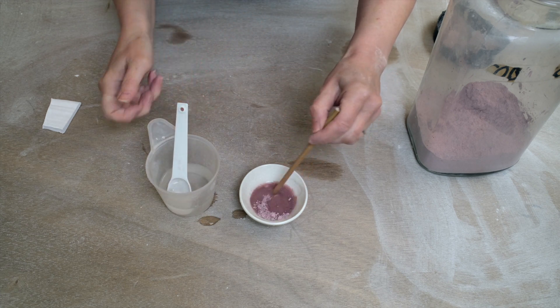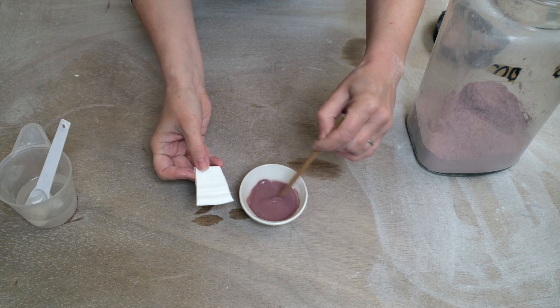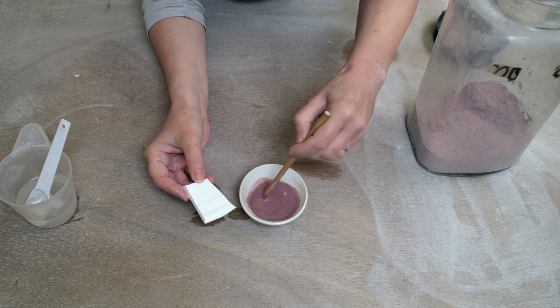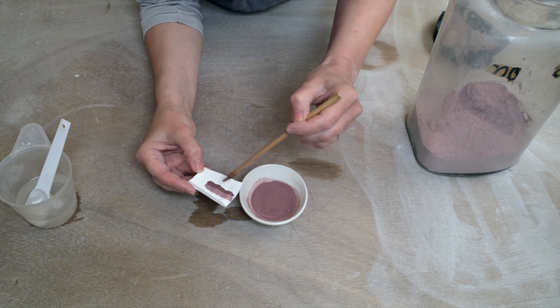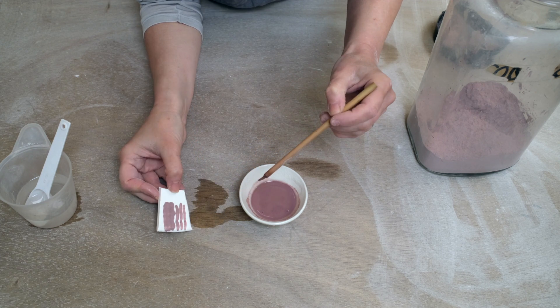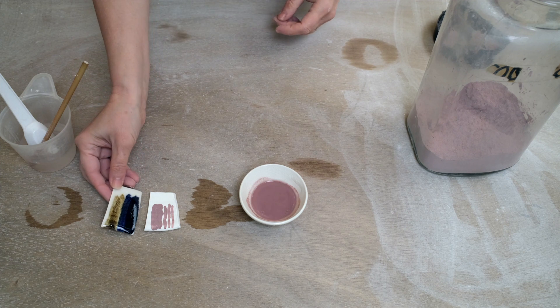You can use a raw oxide or you can buy ready-made underglaze colours. I'm stirring it until it's really well mixed and then I'm going to paint stripes onto the biscuit-fired test tile. This is a porcelain test tile. I'm going to paint various thicknesses of stripes, some overlapping so I'll get a darker colour, and then some fine separate stripes. Then I'm going to cover this with a clear glaze that we made last week so we can see how the oxides look underneath a clear glaze.